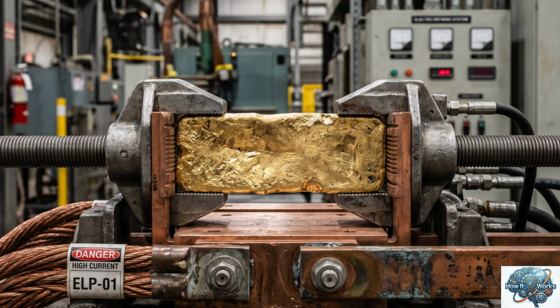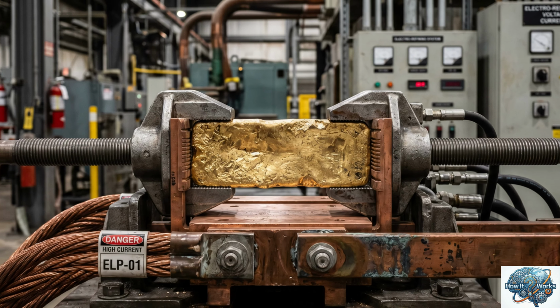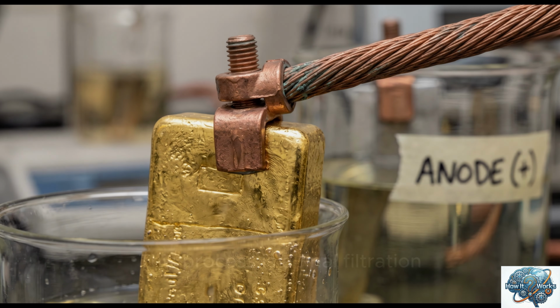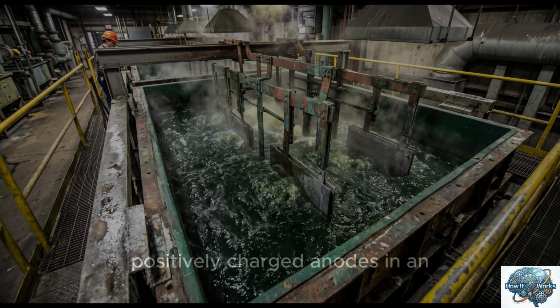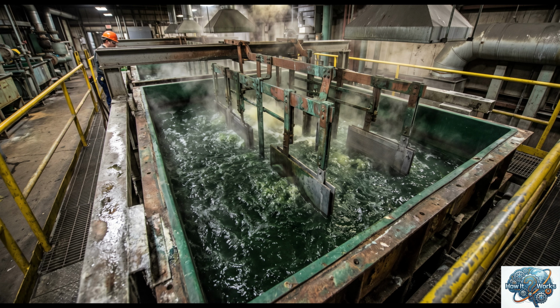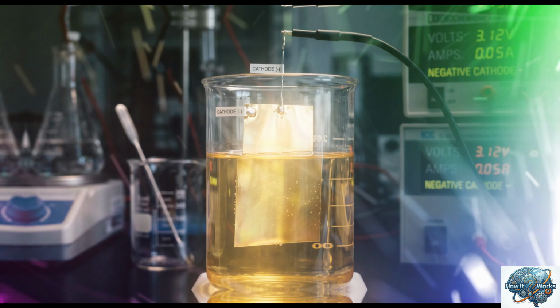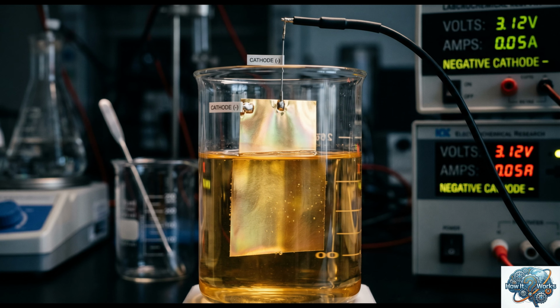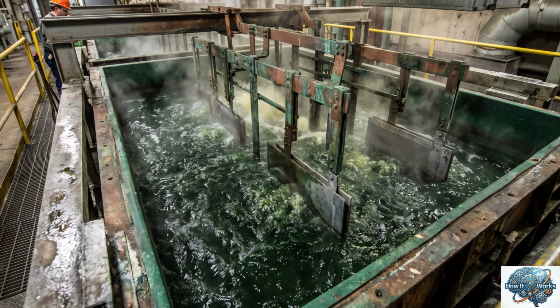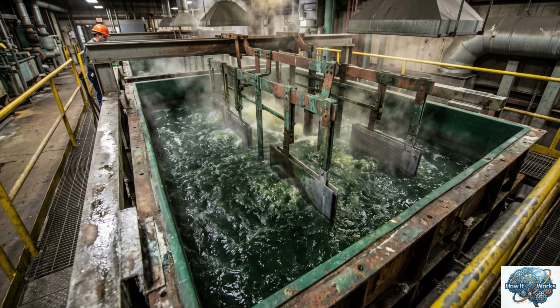For gold used in industrial electronics, an electrochemical refining process begins. This process is a final filtration at the atomic level. The cast gold ingots are suspended as positively charged anodes in an electrolysis tank. Pre-prepared ultra-pure thin gold plates are used as negatively charged cathodes. The tank is filled with an acidic solution based on chlorides with high conductivity.